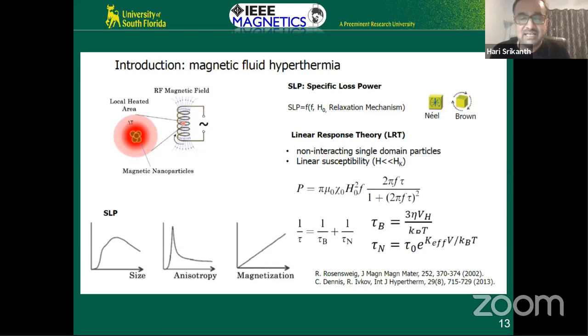In a cellular environment, which is fairly viscous, particles may not have mechanical motion, whereas Néel, or the magnetization rotation, is the more important one. Okay, so here SLP is the same as SAR. This is specific loss power. It's the same as SAR. Some people use SLP. Okay, this one is important because it tells you that one of the simplest ways to increase the SAR, or the heating efficiency, is to make nanoparticles with large magnetic moments, or large magnetization.